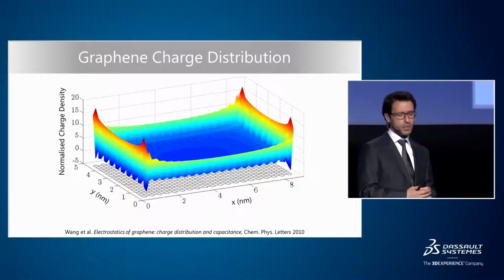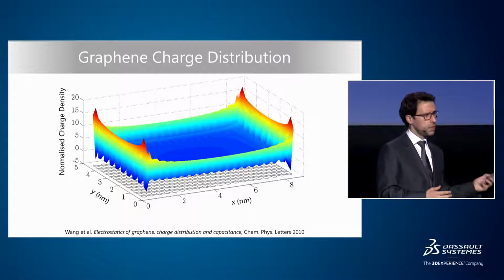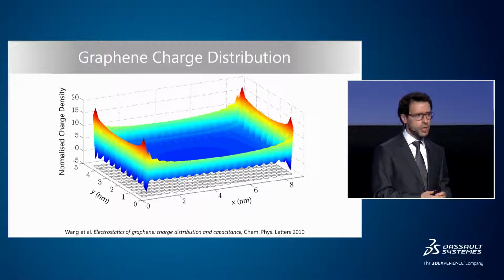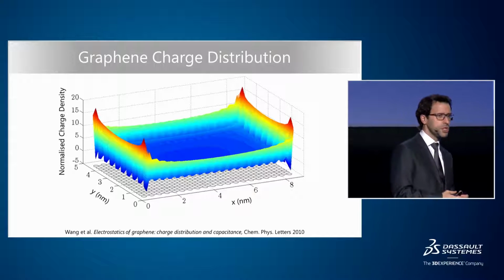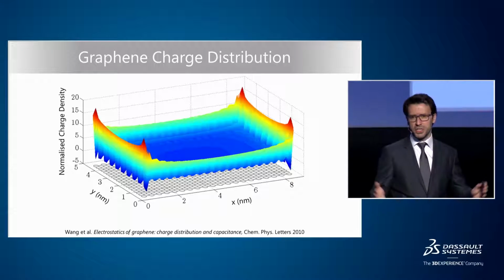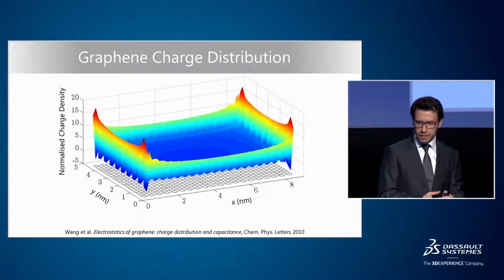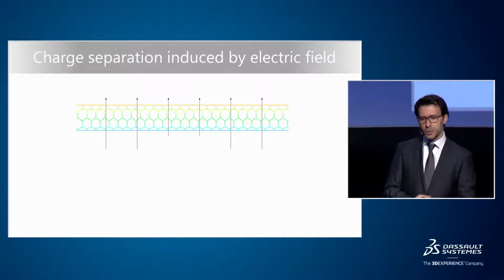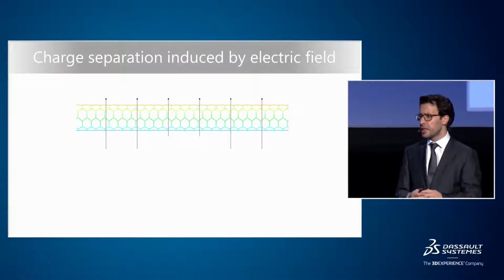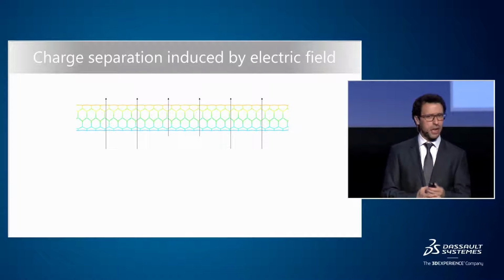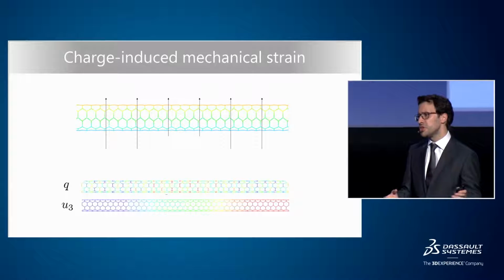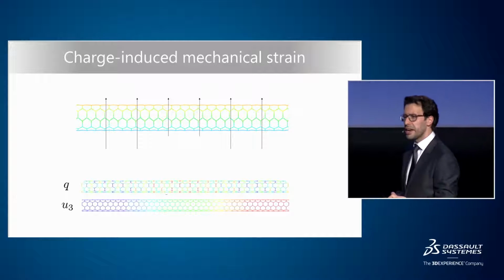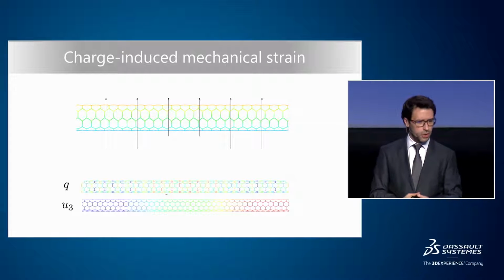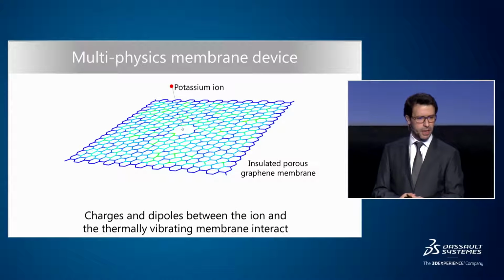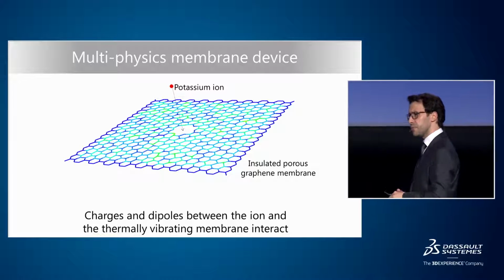This is an example that we compared with literature, where we have a graphene sheet with charge injected, and we see the charge repelling itself. This is a case where we have a separation of charge inside a nanotube motivated by an electric field, and we can also inject charge and obtain mechanical strain as a result and simulate all of that inside Abaqus. In this case, we have a membrane which is at a finite temperature and vibrating.